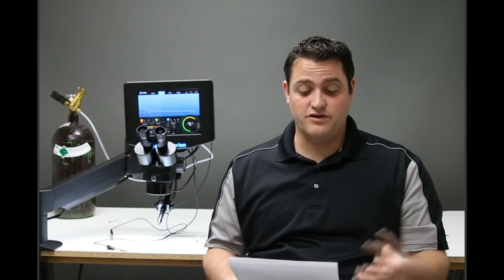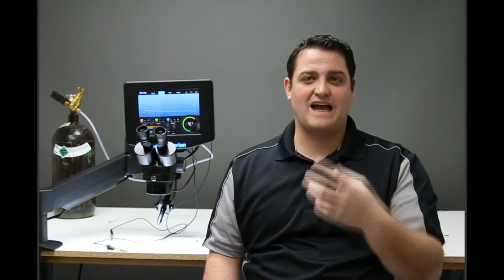Now with the Orion, we can weld any type of silver, but there are a couple of things you want to be aware of, and one of those is zinc. Silver melts at approximately 980 C, which is about where the metal turns molten. On the inverse side, 2160 is about where it begins to boil and becomes unstable. Zinc is much, much lower than that. As the welder is welding and these metals experience very high heat, that zinc tends to boil off, and that's where we get the impurities and the blackness in our weld.